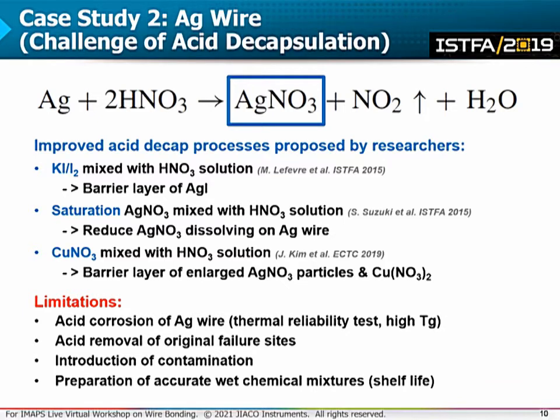Mainly wire pitting and also wire thinning still occurs to a certain extent, and that will influence the mechanical test accuracy. Furthermore, introduced artifacts and removal of original failure sites also affect true root cause failure analysis. Another complication which should not be disregarded is accuracy in mixture preparations and also their shelf life.